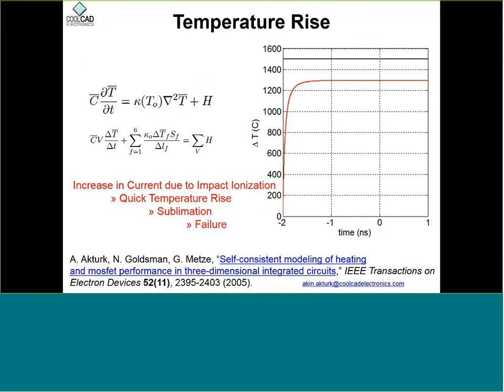And so here I show the sublimation in a very simple way, using a lumped circuit. Here I use the kappas, but these are actually applicable for very small volumes, not for the whole device. So you need to discretize the whole device into smaller volumes to be able to use kappa if you want to use it.